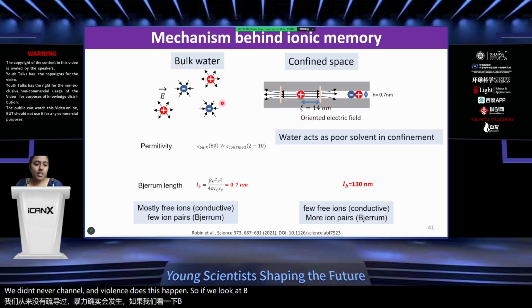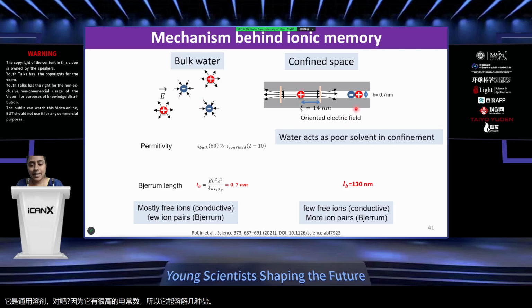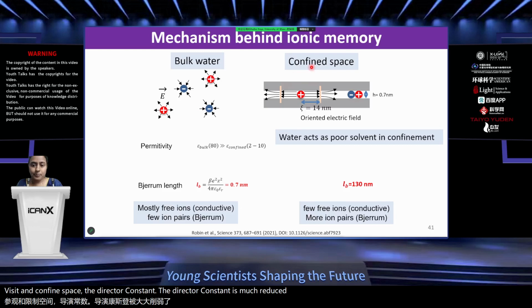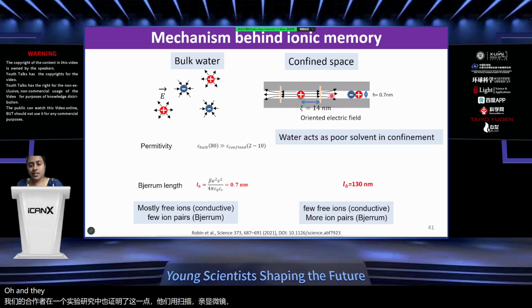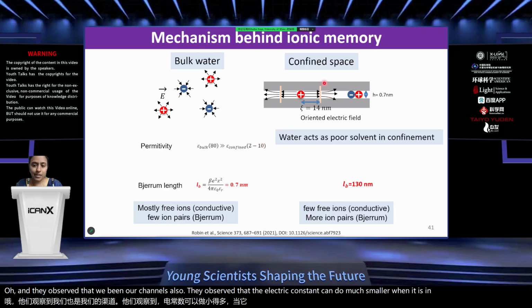If we look at bulk water versus confined water, which is solubilizing our ions, there are ions in water, right? In the bulk water, it's a universal solvent, right? Because it has a very high dielectric constant. It can solubilize several salts. Whereas in confined space, the dielectric constant is much reduced. This has also been proved with one of the experimental studies with our collaborators, where they scanned with scanning probe microscopy, and they observed that within our channels the dielectric constant can be much smaller when water is in confinement.